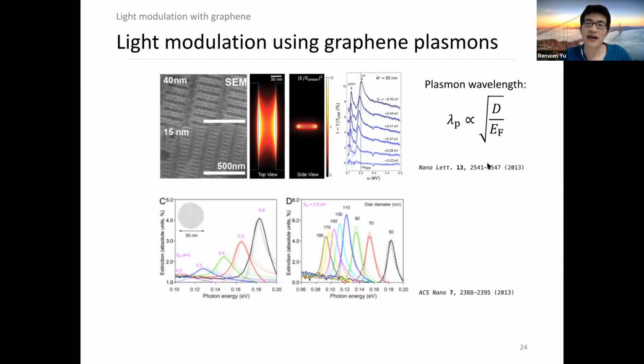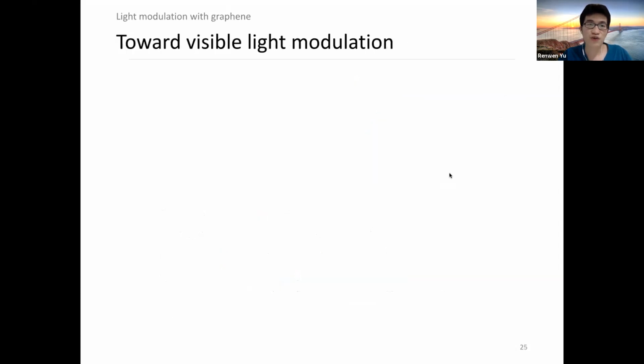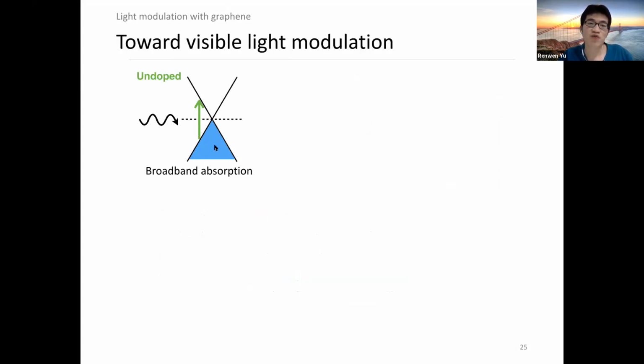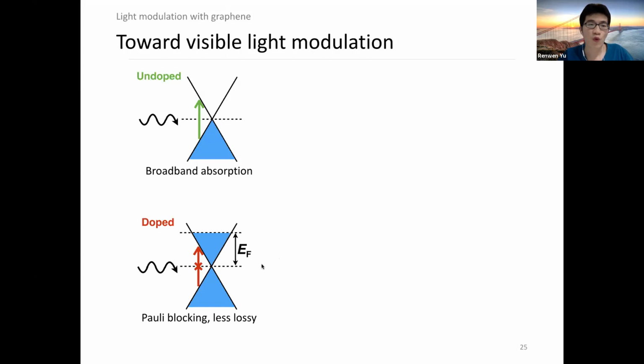So one needs to think of an alternative way to do light modulation with graphene, and the alternative way is to use the interband transition provided by graphene. Here I'm showing again the band structure of graphene close to the K point, the Dirac point. When graphene is undoped, electronic transitions of a broad band of energies are allowed, which makes graphene very lossy in a broad energy range. However, when graphene is doped to a certain Fermi level EF, electronic transitions with energy less than twice the doping level are forbidden, which makes graphene less lossy.